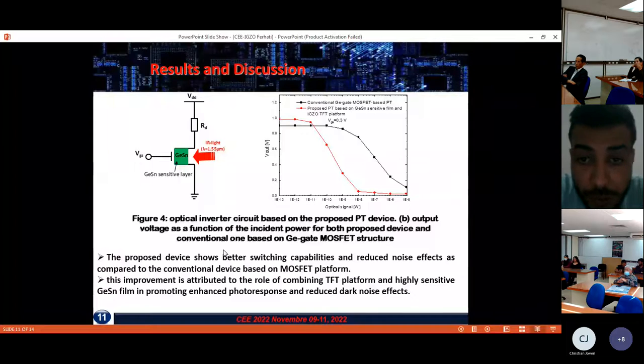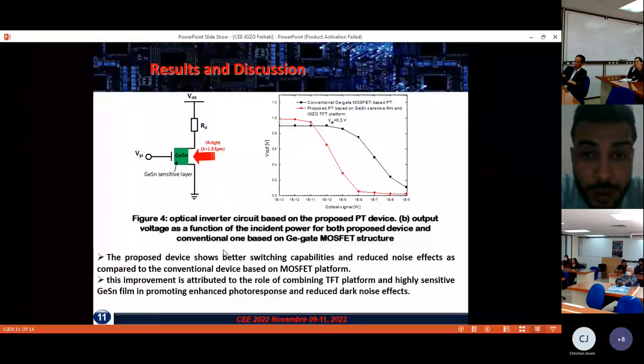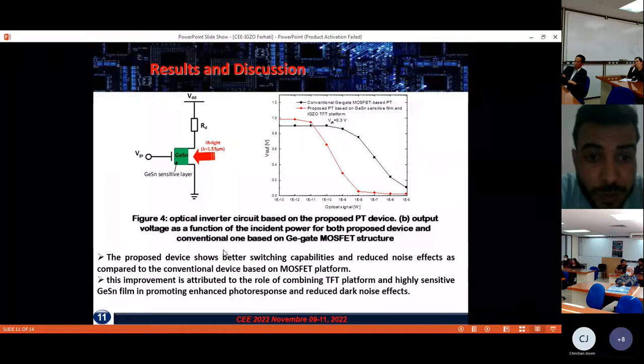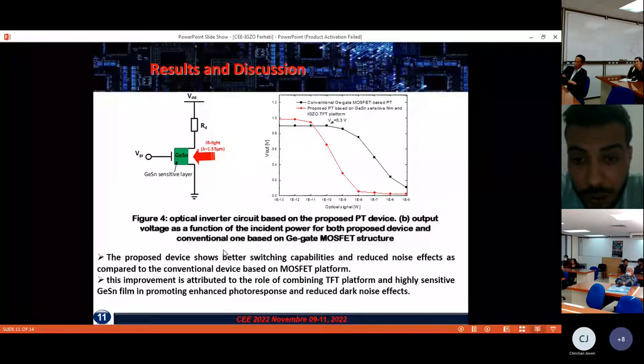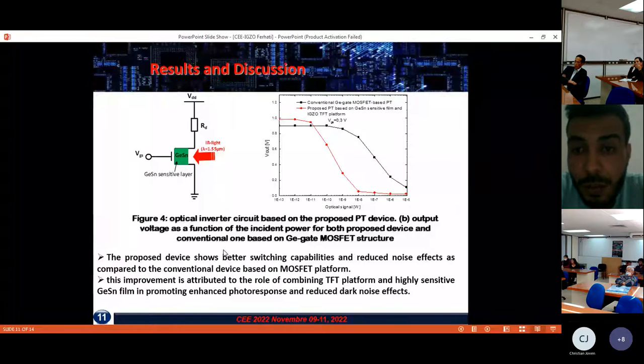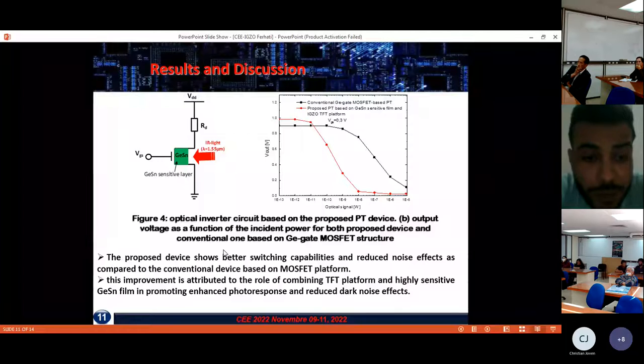To investigate the performance of the device for optical switching applications, the device is implemented in an optical inverter gate circuit, and the output voltage as a function of the optical signal for both the conventional germanium gate MOSFET and the proposed device based on germanium tin and indium gallium zinc oxide thin film transistor platform are given in this figure. It can be seen from this figure that the proposed device shows better switching capabilities and reduced noise effect as compared to the conventional device based on the MOSFET platform. This improvement is attributed to the role of combining the thin film transistor platform and highly sensitive germanium tin film in promoting enhanced photoresponse and reduced dark noise effects.